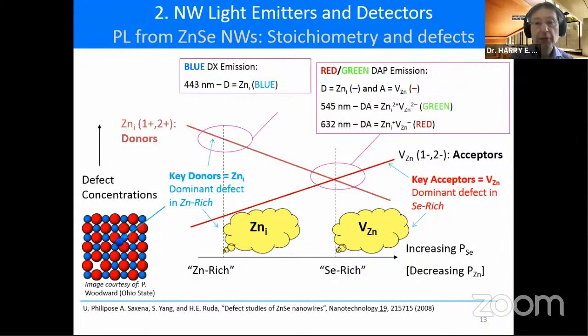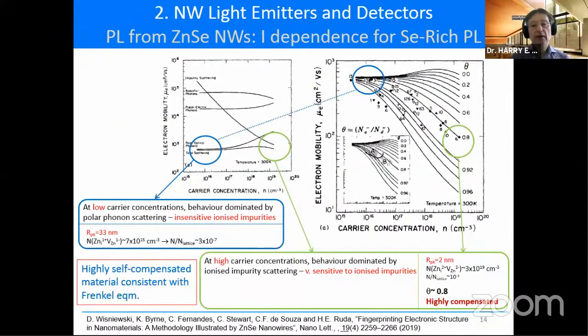So can we put this story together? Well, let's start just to finish that on the selenium-rich side. What I didn't mention is we also looked at taking these single nanowires and putting contacts on them. And if you look at the carrier concentration, in fact, it is in the high 10 to the 19 kind of numbers. And obviously then the wires are highly compensated, as you'd expect, by having roughly equal concentrations of donors and acceptors.